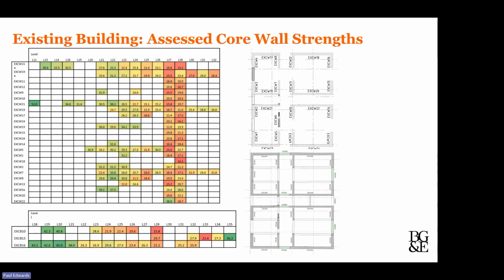You'd have been talking about 15 stories where each core wall would need to be strengthened either by steel jacketing in most instances, and maybe also where tension was an issue in carbon fiber plating. The costs of that would have been tens of millions of Australian dollars, which is quite a large increase in the overall budget. So the decision was made to undertake a much deeper assessment of the existing concrete walls to try and understand exactly what the minimum level of intervention would be to achieve the desired overall strength of the existing core. And this table starts to pick up some of that more detailed investigation where you can see some of the identified destructive core strengths developed and starting to focus down a lot more on just a couple of floors rather than a group of 10 to 15 floors.